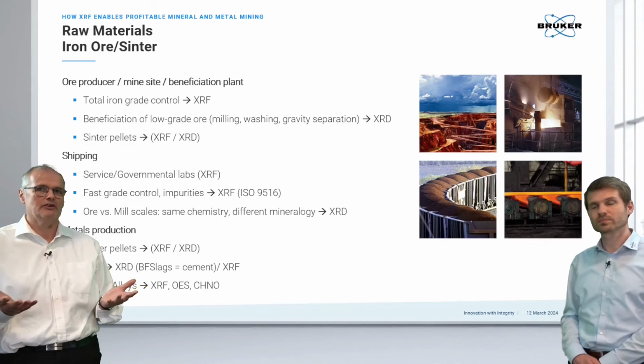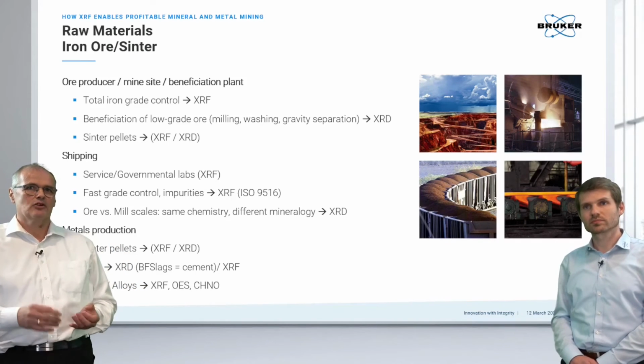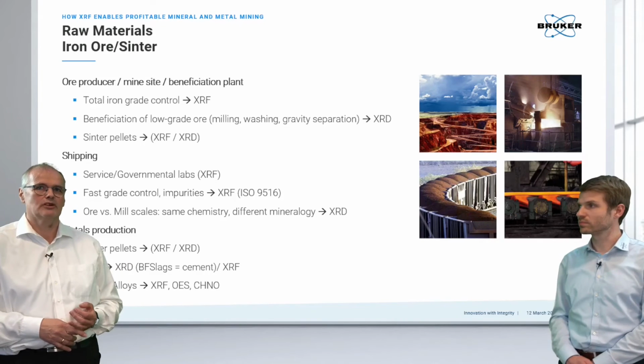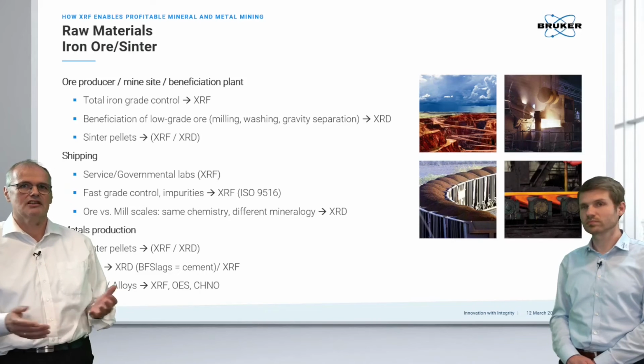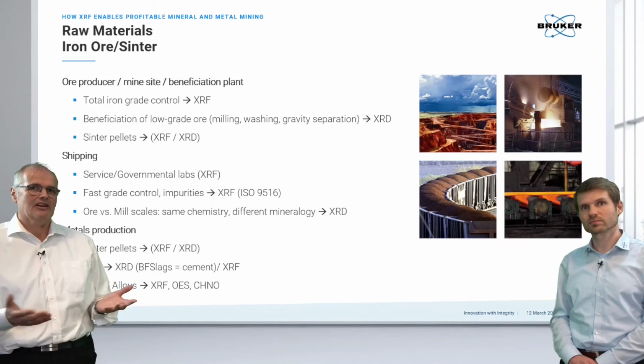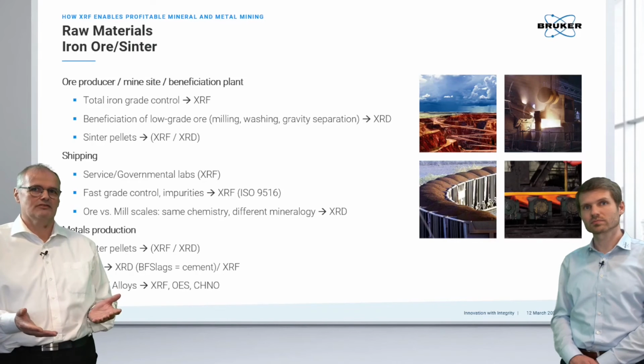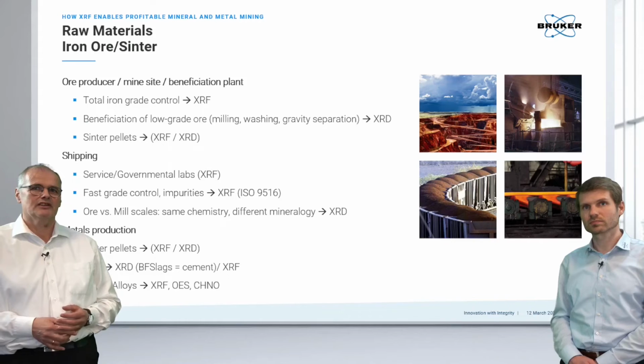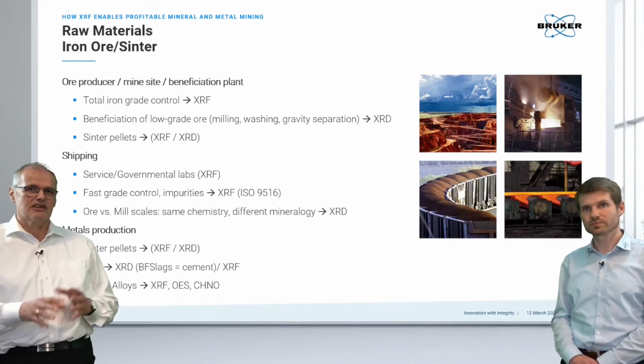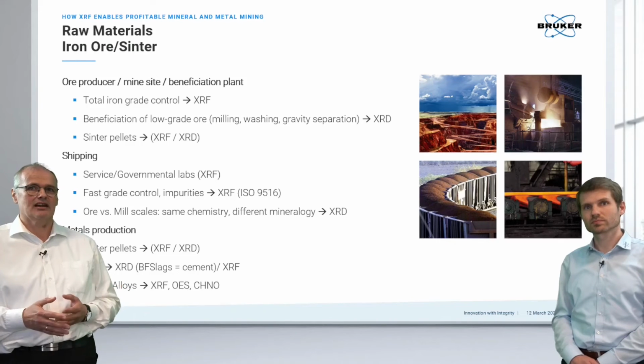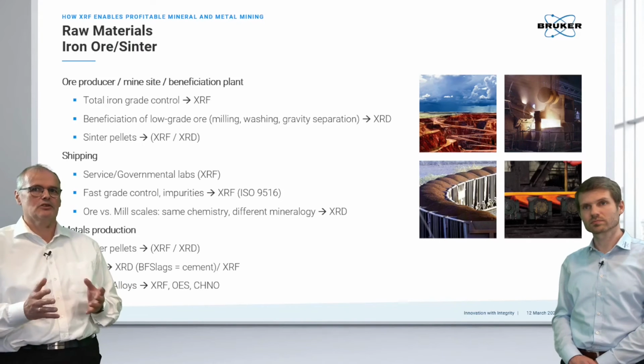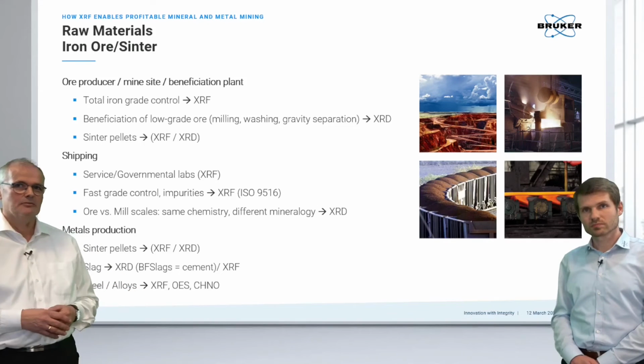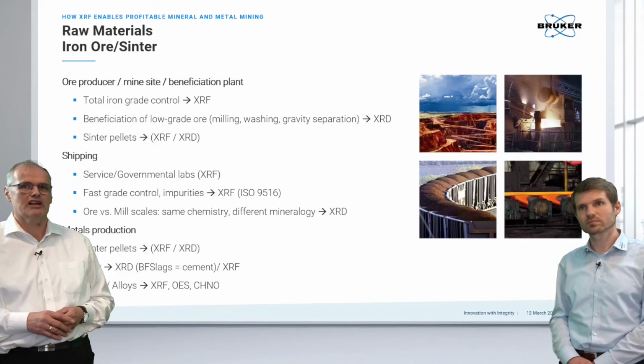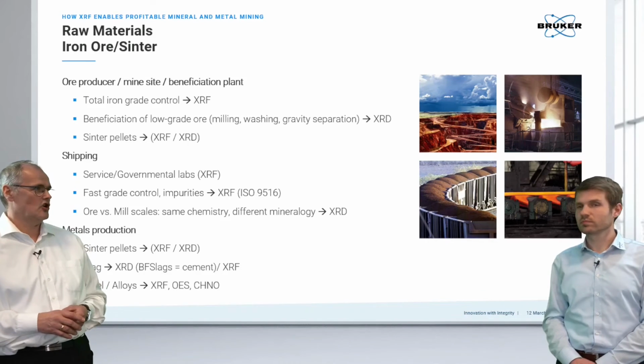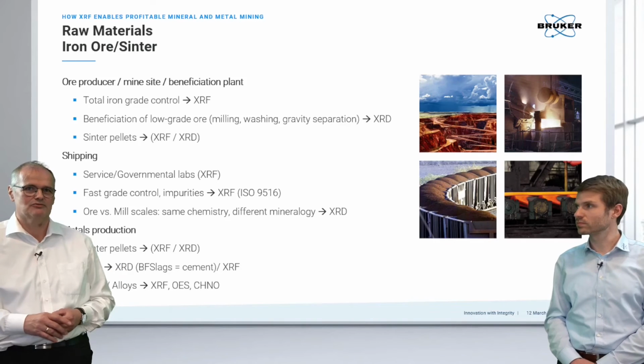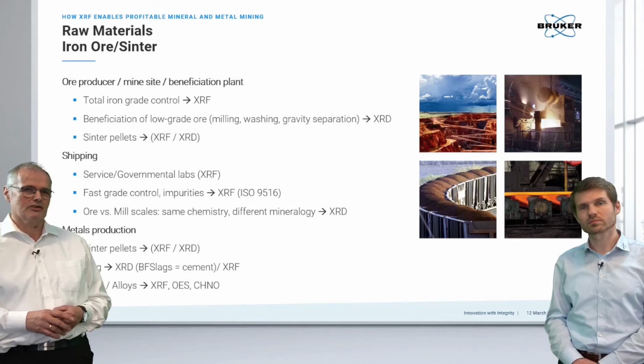When we talk about iron ore, we talk about a huge amount of tons. And of course, the ore producer itself is looking for total iron ore grade, beneficiation, the milling, washing, the gravity separation, the sinter pellets, and of course the shipping. And in all those cases, XRF is involved, especially the fast grade control, where we have an international norm called ISO 9516. This tells us how it's accurately done. The goal is maybe not to be perfectly right, but to have comparable data across the globe. Because you can imagine that it's tough negotiation when you have a deviation between Australia, China, or Australia and Germany, about 0.1% deviation, right? And then, of course, we find XRF and XRD also in the metal production itself.